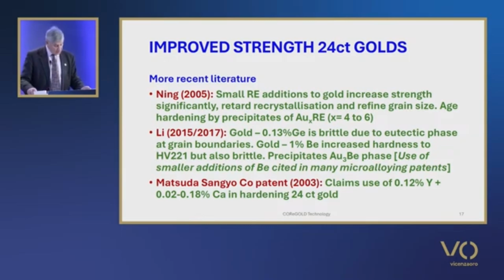In a study of a gold 0.13% germanium alloy, Li characterised the cause of brittleness that he found. The gold germanium phase diagram is a eutectic system. He found that germanium tends to segregate to grain boundaries as a eutectic phase, which led to the brittleness. In a further study, he reported work on hardening of fine gold by 1% additions of beryllium, and he found that the beryllium addition increased the hardness of gold to about 221 Vickers, but that the alloy was brittle and fractured on attempts to roll it.